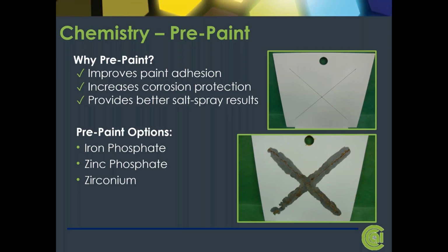But what I'm going to focus on mostly today will be the zirconium pretreatments. It's a phosphate-free product. It runs at room temperature. It's based on nanocrystals, so you don't use coating weight to measure this. It's almost unmeasurable. You'd have to have a very sensitive measuring device. But it's clean chemistry. It gives you very good paint adhesion, corrosion protection, and it's becoming more and more predominant in the industry today.